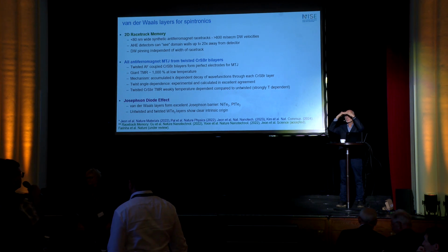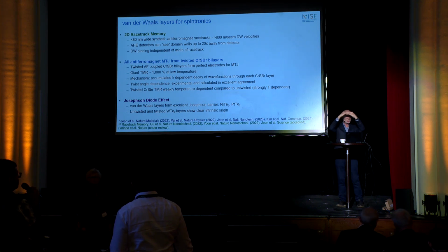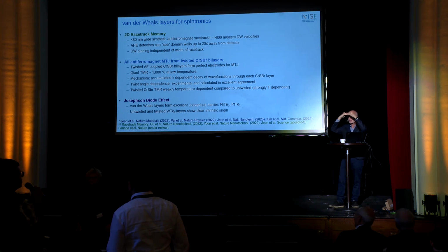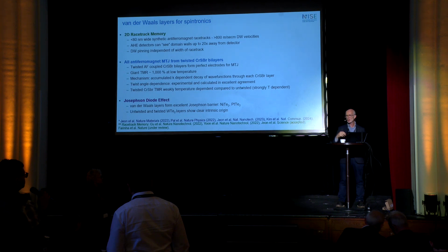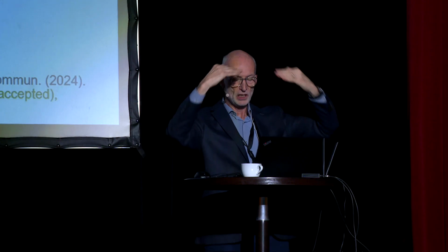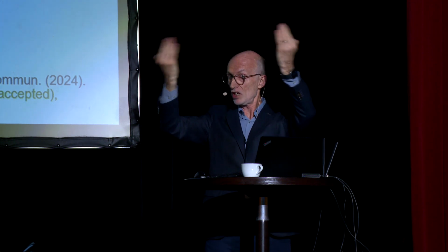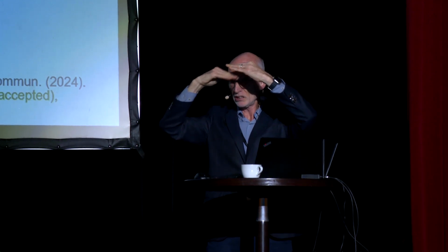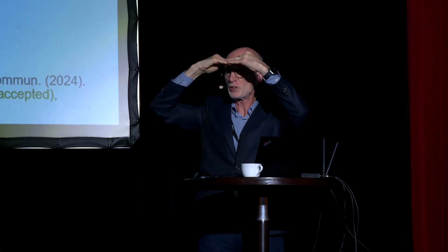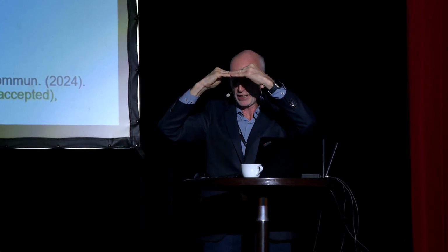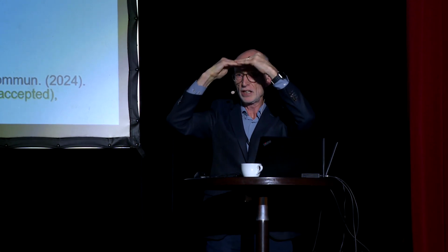Chromium sulfur bromide typically tends to be heavily doped. No, it's not doped. It's undoped. I see. But it's not a priori obvious to me that it would be better to have an undoped semiconductor versus a doped one. Do you know what the answer is theoretically? Well, theoretically, for our tunneling junctions, we want it to be undoped because we want them to act as a tunnel barrier. If it were doped, then we would not see that. Of course, many Van der Waals systems, I'm not sure which doping you're referring to, but let's say the 2D magnetic systems, you can dope them with iron. Super interesting. It goes into the Van der Waals gap, and we've demonstrated we can see spin glass behavior. Maybe it doesn't answer your question, but I think doping is interesting, not for semiconductors, but actually magnetic doping to generate novel magnetic states.